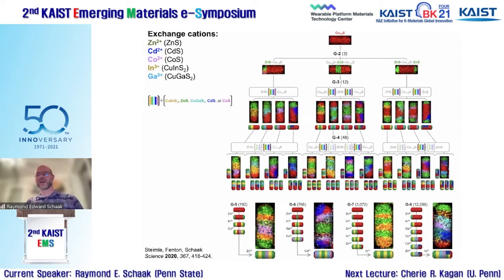metal sulfide nanorods, all starting with just these three templates that themselves derive from just a single type of copper sulfide rod. And what I'm showing here, obviously you can tell what are cartoons. These are actual data, the STEM EDS element maps for the ones that we observed experimentally. And then these down here show the total synthesis. So for this one here, each of these exchanges is a separate step, and it shows what the process was that we took to make it. And I would argue this is probably one of the most complex nanoparticles in terms of the scope and number of materials and interfaces. I think it's something like 6 materials and 8 segments and 11 internal interfaces or something. And these are all as uniform 20 by 50 nanometer colloidal nanorods.